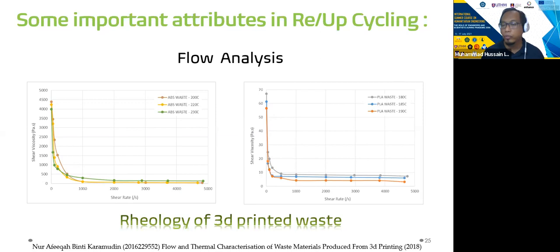I believe that maybe some of you are familiar with 3D printing. For the filament, normally the temperature is set at 180 to not more than 250 degrees Celsius, depending on the materials. For example, for PLA waste, it is found that at temperatures of 180 to 190 degrees Celsius, we can see a similar trend. The viscosity is not really high, less than 100 Pascal second. But when we compare with the ABS, that's why ABS is quite tough for applications that require certain strength.